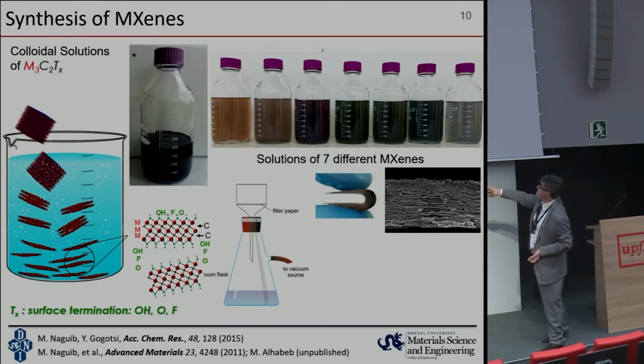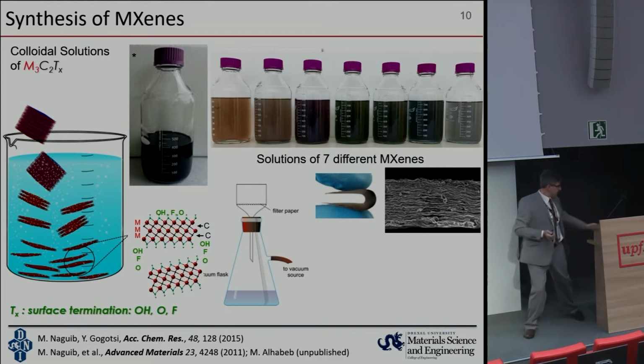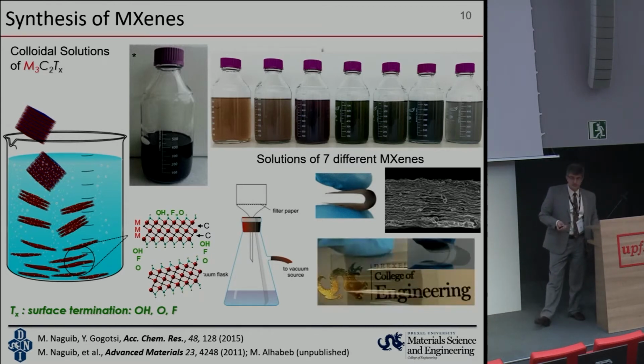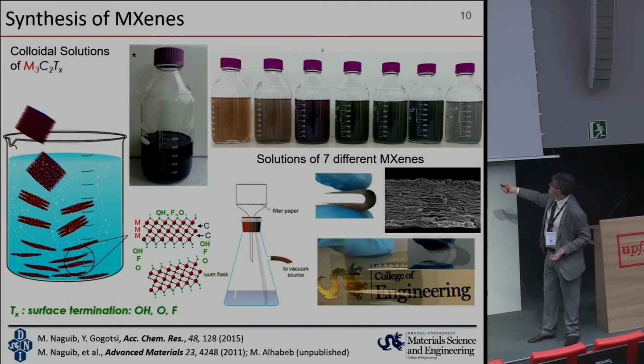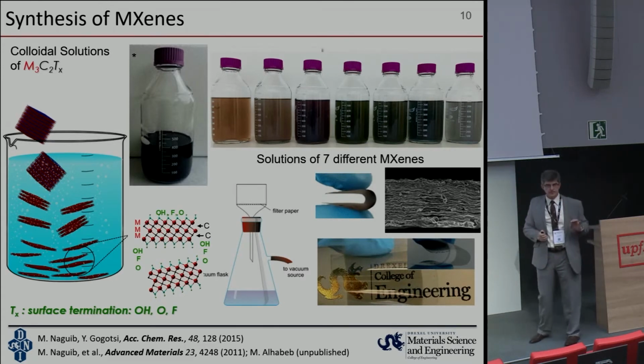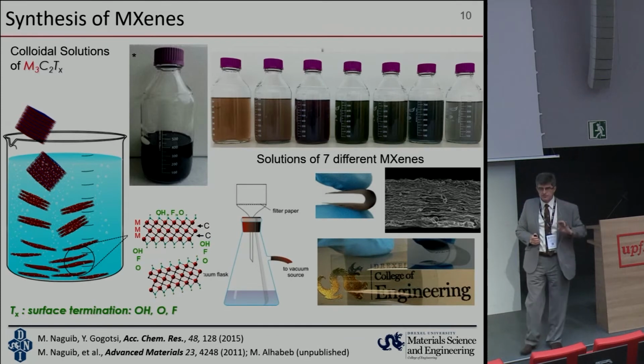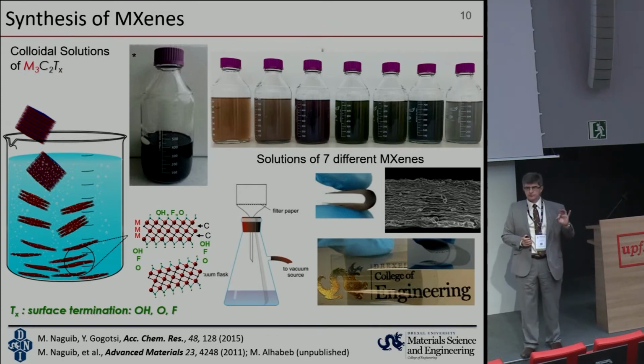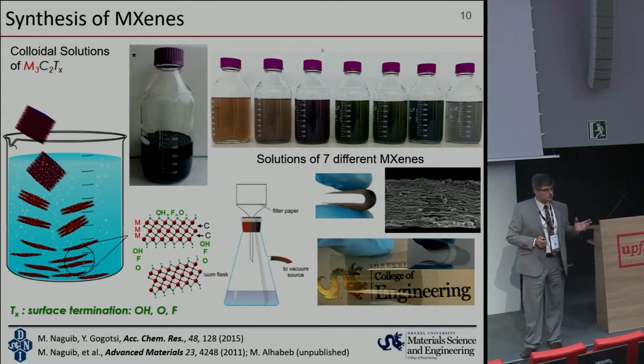We can do vacuum-assisted filtration, for example, make these films with flakes aligned parallel to the surface. They'll be flexible, very nice, easy to handle here. We can spray coat them. For example, you can see here a coating on a polymer film. The coating is transparent because, for example, titanium carbide Ti3C2 MXene absorbs about 3% of visible light per 1 nanometer. Graphene absorbs 2.3% of visible light per nanometer.